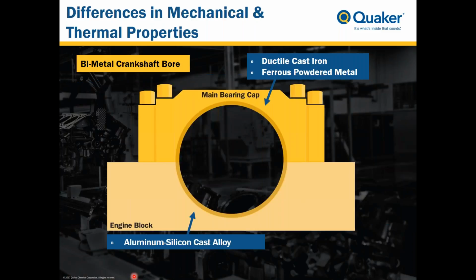So let's look first at the mechanical and thermal property differences between the materials. What's shown on this slide is a very general schematic of the crank bore. And what you can see is on the bottom, in the lighter yellow, is the engine block. And on the top is the main bearing cap, which is typically a ductile cast iron or a ferrous powdered metal. Again, the engine block is usually a high silicon containing cast aluminum alloy, such as a 356 or a 319, or in some cases even a higher silicon containing alloy like a 380. And right here is the bore that needs to be finished.